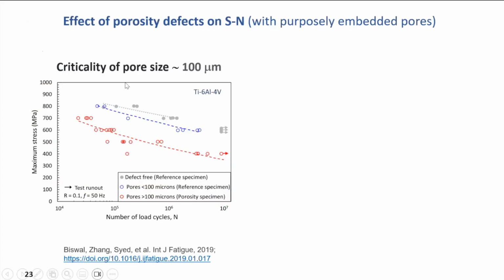The first study we did about 9 years ago is we printed gas pores in our samples. And we found this: applied stress versus number of cycles to failure. The pale gray is the benchmark without porosity. Then the blue, we actually found some porosity, but it's our reference specimen without contaminated wire. They do have naturally occurring pores, much, much below 100 microns. The red ones are the pores greater than 100 microns.